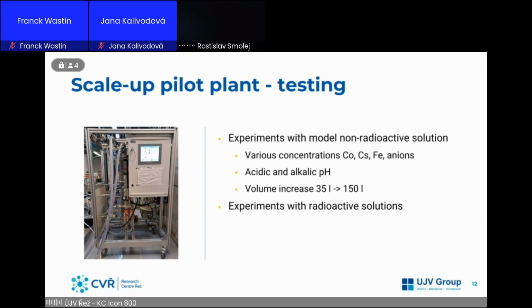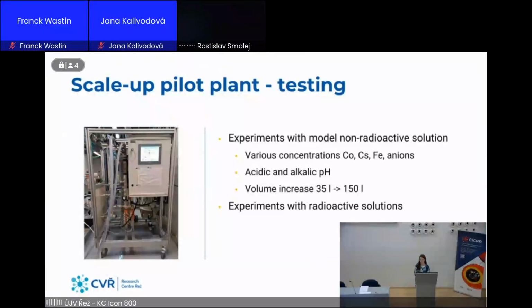Before we did the test with the real radioactive solutions, we tested our scale-up plant with the non-radioactive solution. Again, we varied the concentration of the focus elements, which was cobalt and cesium, and then we increased the volumes of the process waste up to 150 liters, while we still have some work to do, and our top limit for the volume is 600 liters.